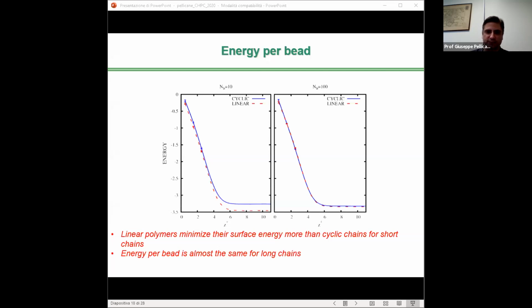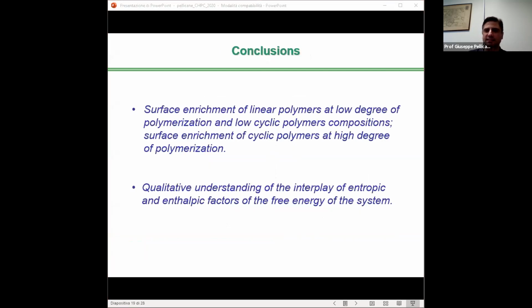So let's try to summarize the results that we showed in terms of entropic and enthalpic contributions to the free energy of the system. At low degrees of polymerization, when cyclic polymers reach the surface, their conformational entropy decreases because of their folding. For the same reason, for being partially in contact with the empty space, their energy also decreases. So at the interface, linear and cyclic polymers should get a similar loss of conformational entropy when we consider short chains. However, the entropy overall increases because chain ends at the interface have a positive entropic contribution, which favors linear polymer enhancement at the interface.